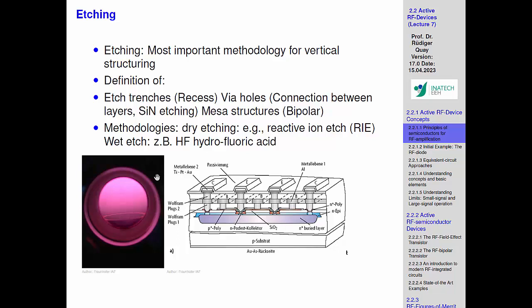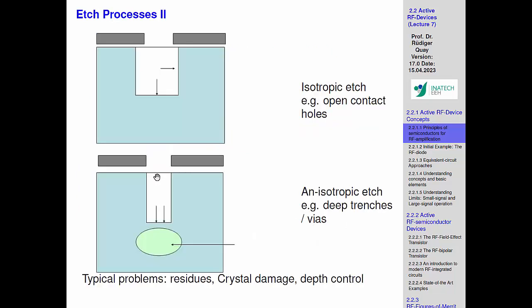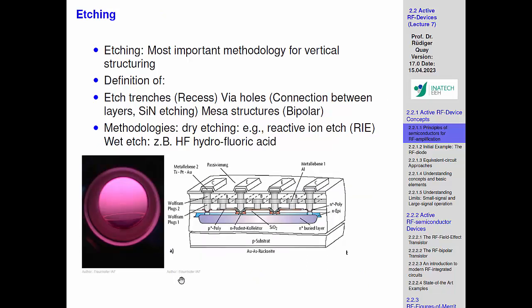So it's not only that you take the chemical exposure, so that it just etches, but that you also shoot at the crystal with some accelerative bias of the gas. The trouble is, and remember we were talking about single atoms, so you want to expose a trench, but you want to stop underneath, because here could be the active transistor, and if you hit the crystal too hard, then you will also kill the conductivity of the active device. So what is very special is to have these.